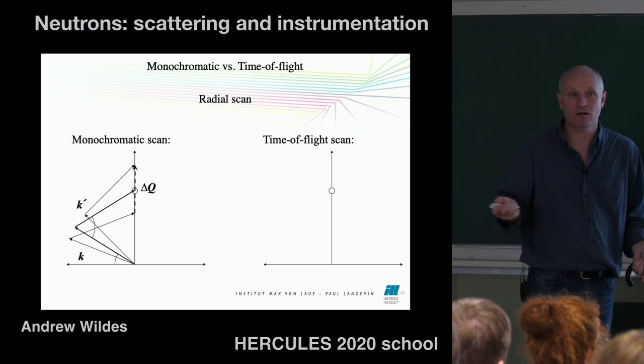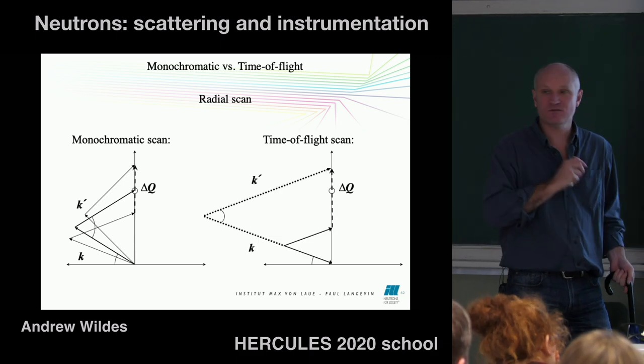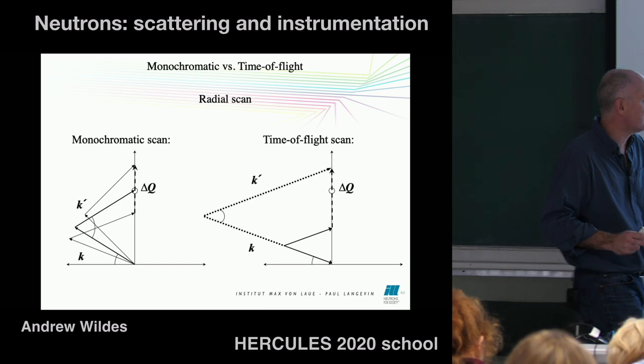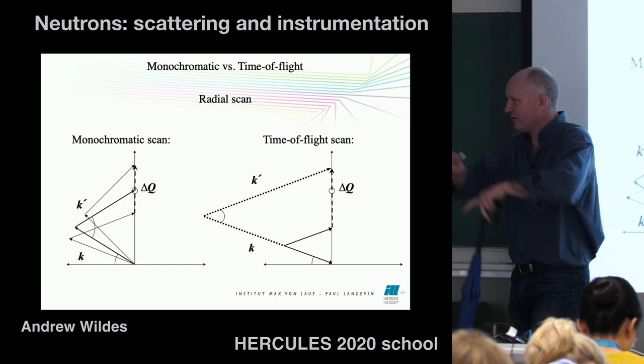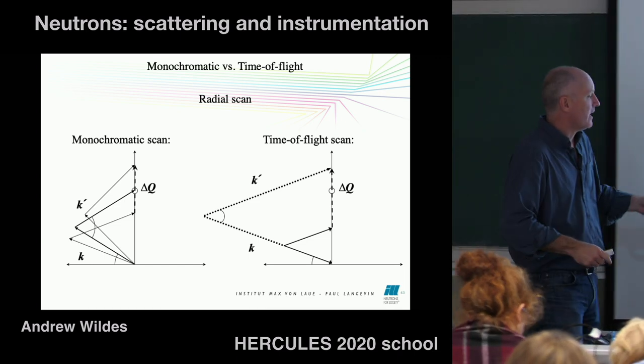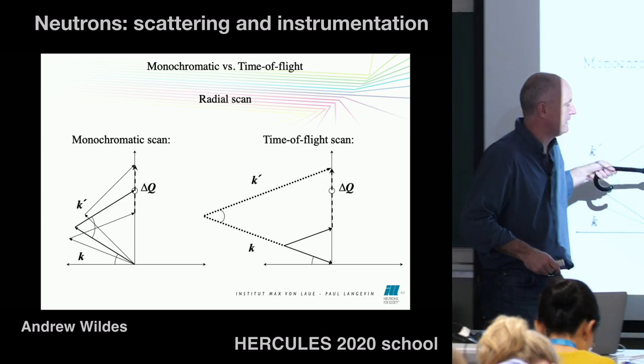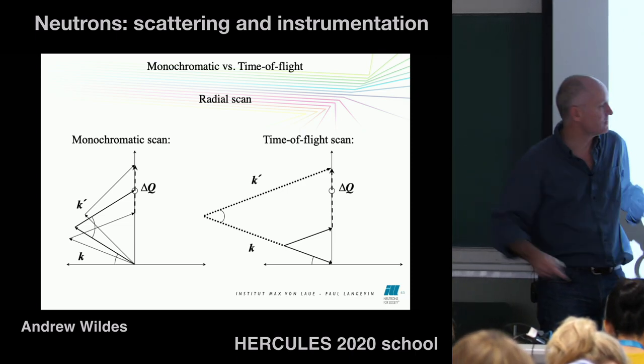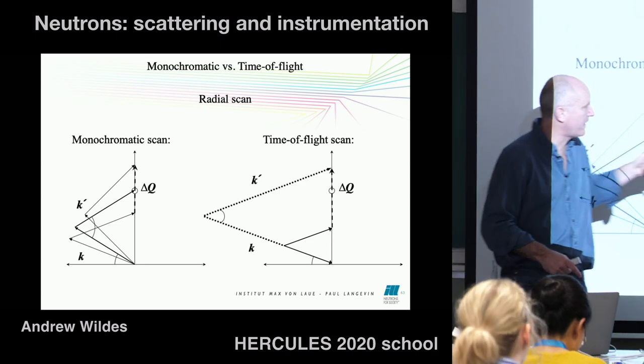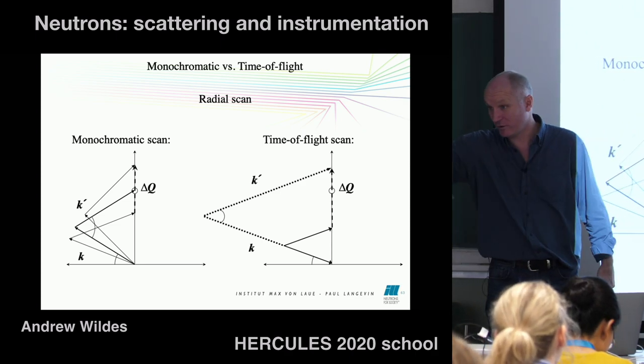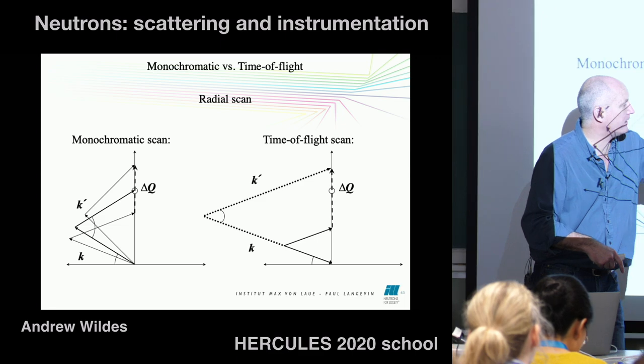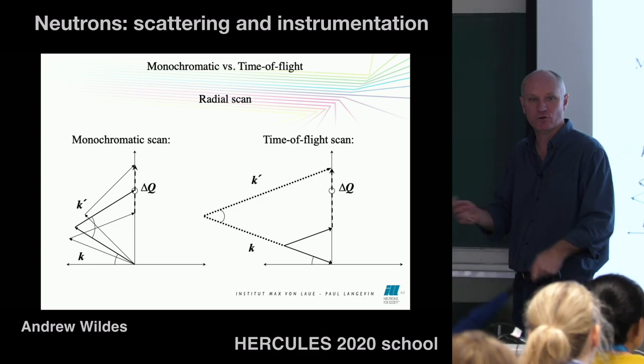You want to do the same thing in a time of flight experiment. You don't have to move anything. In this case, you set up the angle of your crystal, and you set up the angle of your detector. And then you use the time of flight to work out what your initial length of k is, and the time of flight to work out what your final length of k is. And if you assume all the scattering is elastic, you're automatically covering this trajectory without having moved anything.